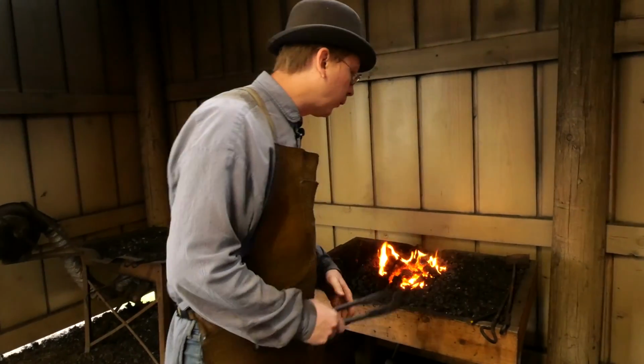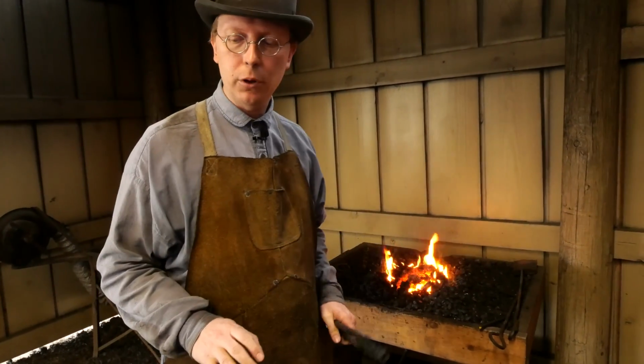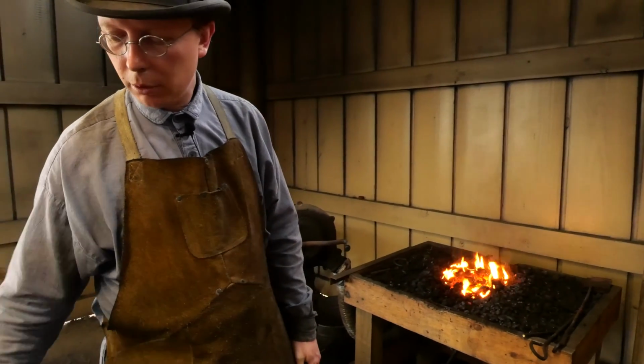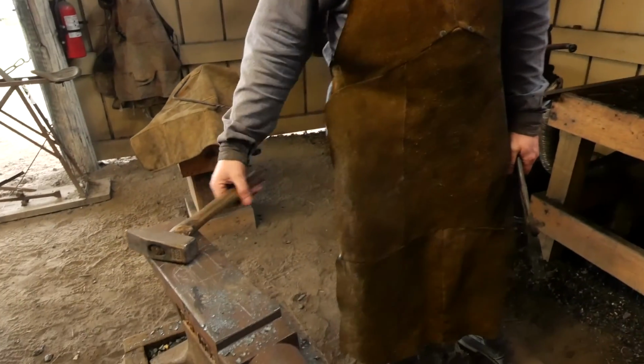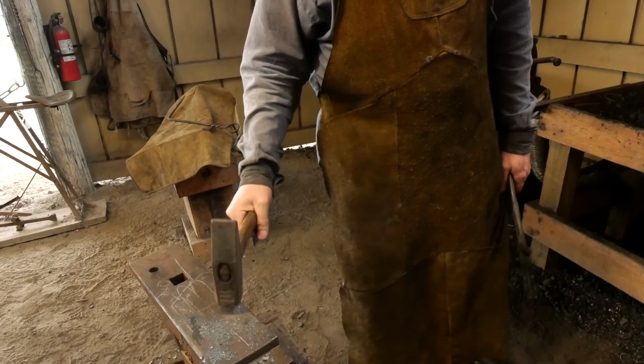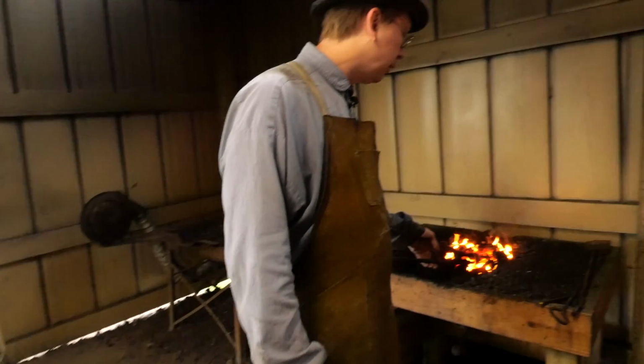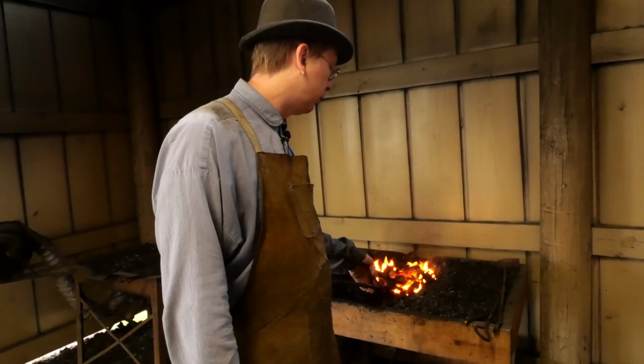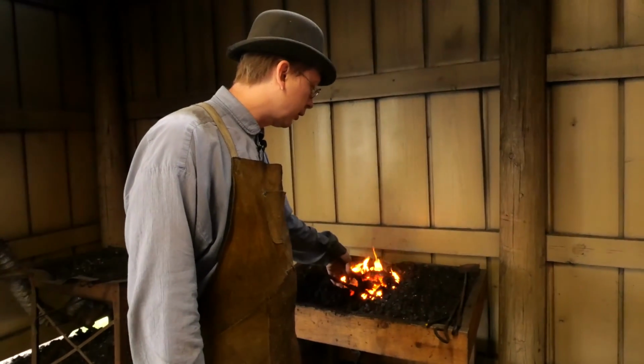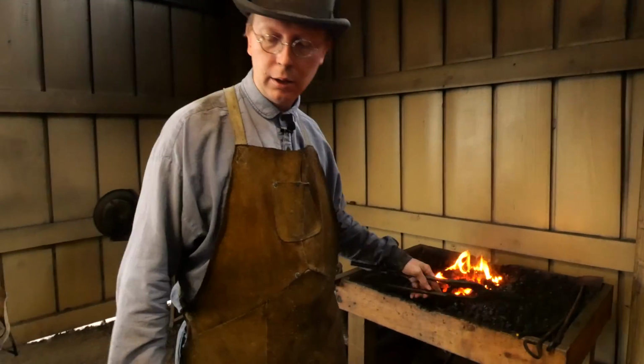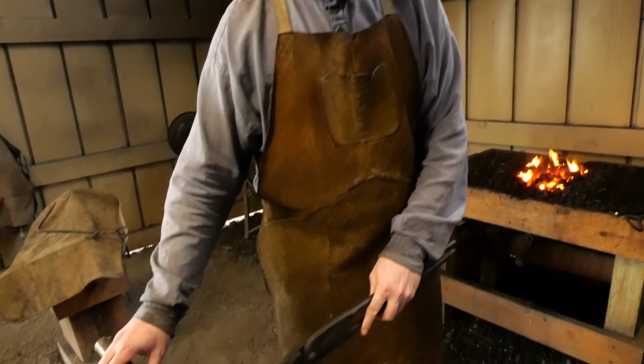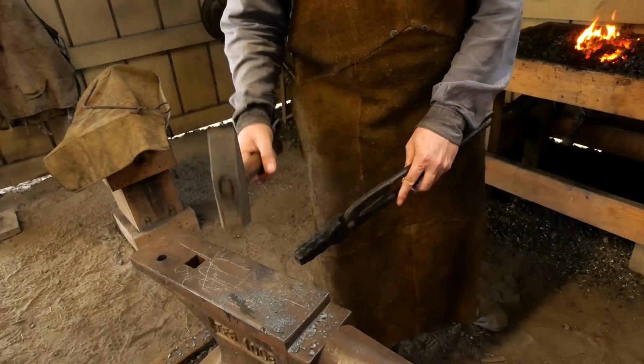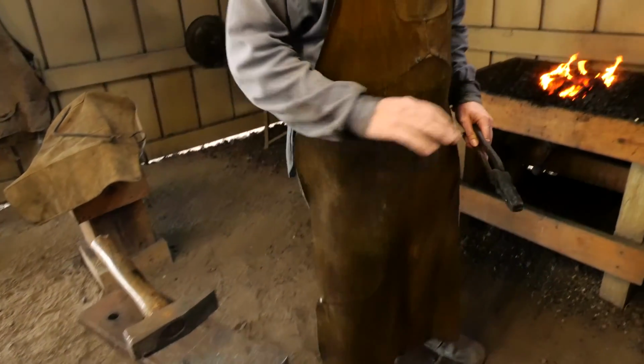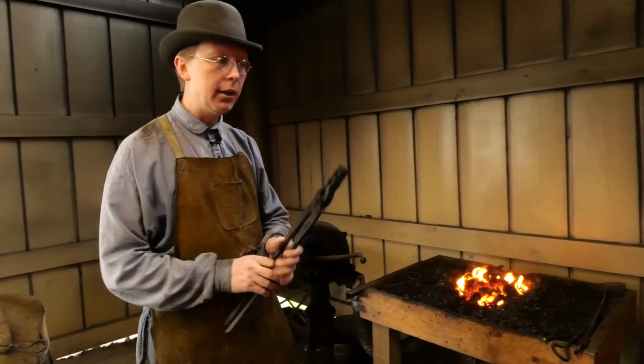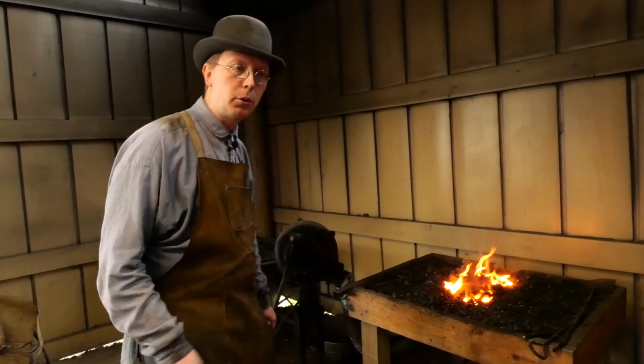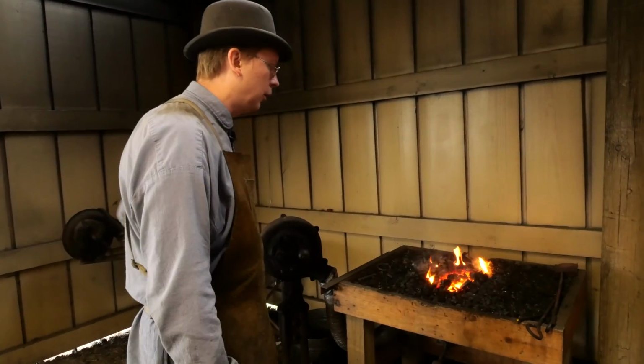You may have noticed on the first one too, when I go to do my forge welding, I make sure that I know exactly where my hammer is going to be, the direction it is, so that I can pick it up and be 100% ready. And a lot of times, especially with smaller steel, I'll pull it out of the fire, be positioned in between my forge and the anvil, and go to hammer without even having to take a step. Need to do this very quickly so that it doesn't cool down too much and get below forge welding temperature.